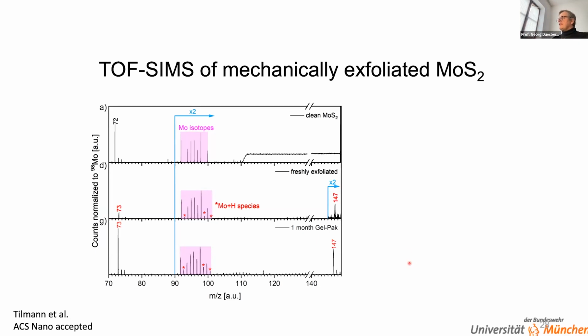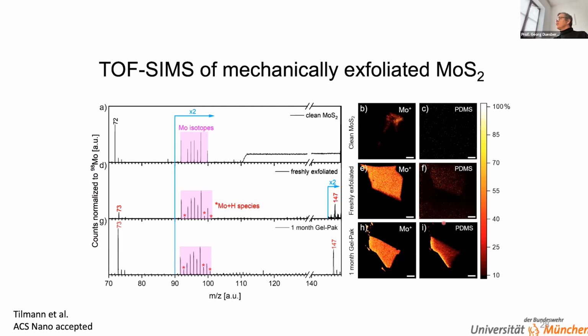And to prove more or less our story, I can show you this. These are flakes that had been stored simply for 1 month in a gel pack, the typical packs where you can store your samples in, and those PDMS peaks shoot up at the same time. This Mo plus hydrogen peak should go up in the ToF-SIMS spectra. So what this shows is if you have samples laying around in your storage area or on a gel pack, the PDMS will basically move or absorb onto the MoS2, and this can be even imaged here.